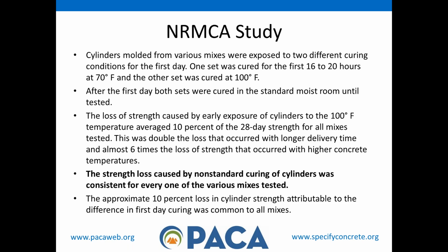The loss of strength by early exposure of cylinders to 100 degrees Fahrenheit averaged 10% of the 28-day strength for all mixes. This was double the loss that occurred with longer delivery time, and almost 6 times the loss of strength that occurred with higher concrete temperature.